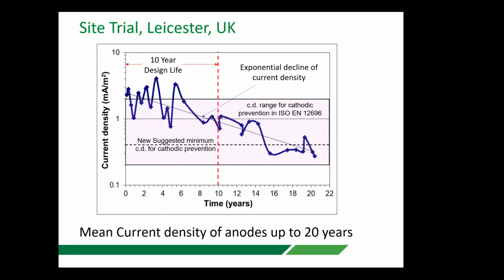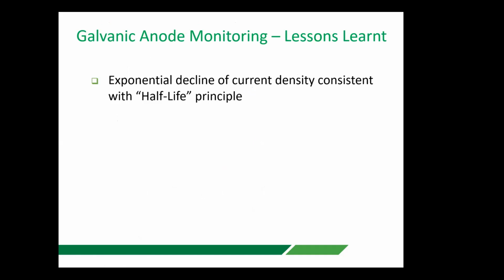And if we look at the mean current density over that period of time, you could see that at 14 years, that's dropped considerably. But nonetheless, we could see that if we plotted on a logarithmic scale, the decrease in the current was actually exponential. So you had basically a straight line relationship. And we could determine, if you like, an aging factor. The aging factor being how quickly the current halves from its original value. So in this case, we saw that at 7 years, it roughly halved, and 7 years more, it halved again, and so on. So there's an exponential decline of current density, consistent with the half-life principle. That makes things quite easy in consideration, because you can then try to design accordingly.